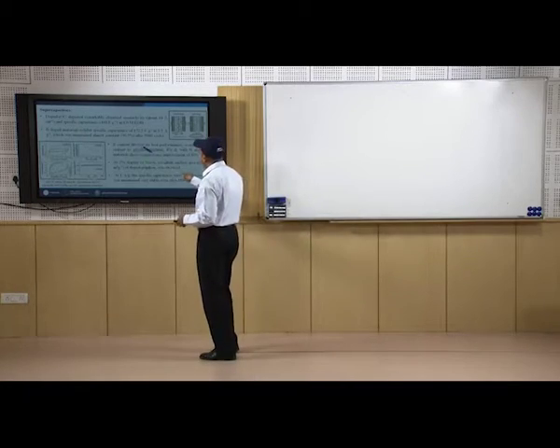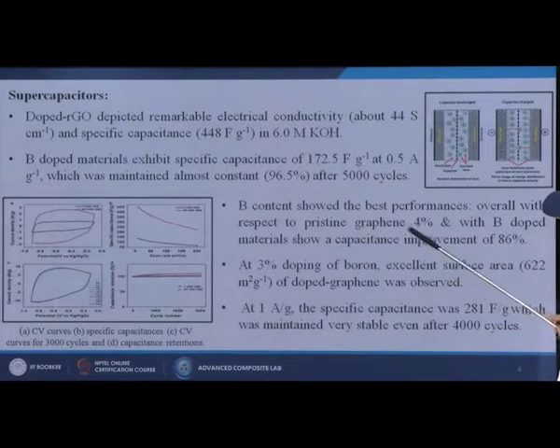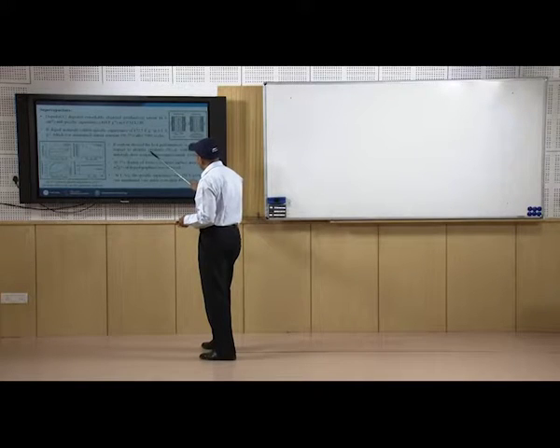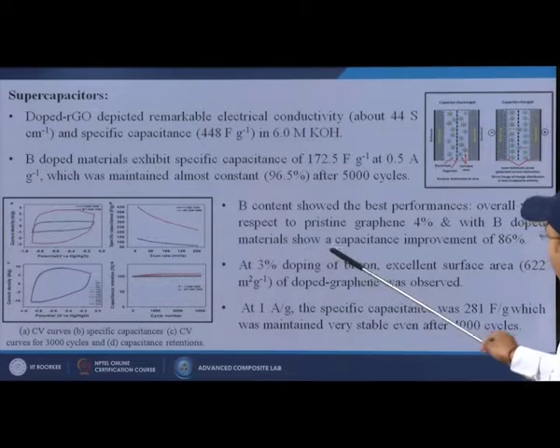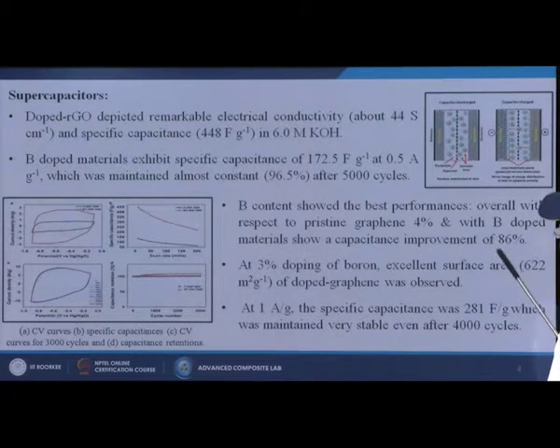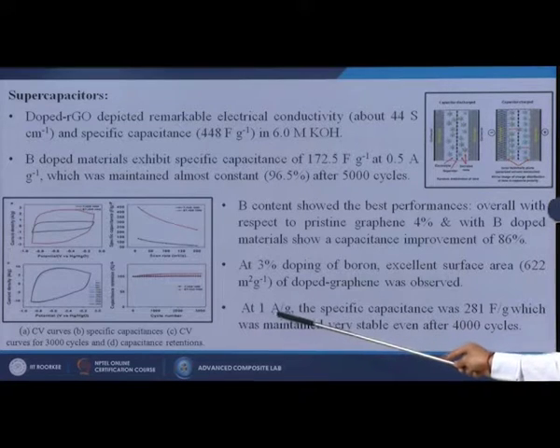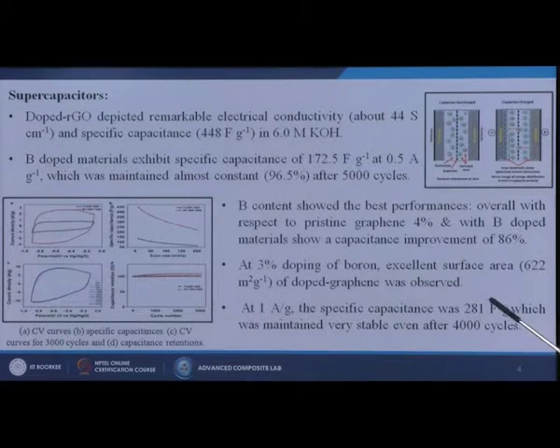Also, the 4% weight boron content showed the best performance overall with respect to pristine graphene, and the boron doped materials show a capacitance improvement of 86%. So you see that when we are using the pristine graphene, that percentage is around 4%, but when we are using these boron doped materials, the capacitance improvement is more than 86%. At 3% doping of boron, an excellent surface area, 622 meter square per gram of doped graphene, was observed. At 1 ampere per gram, the specific capacitance was 281 farad per gram, which was maintained very stable even after 4000 cycles.